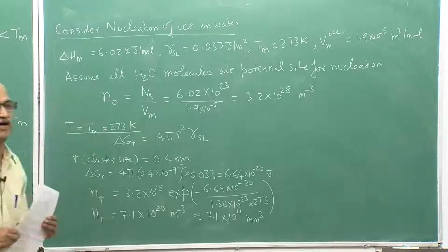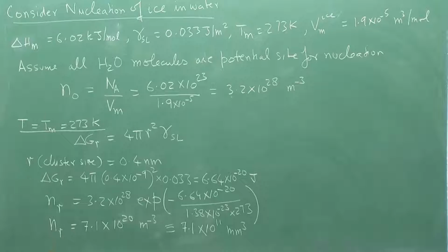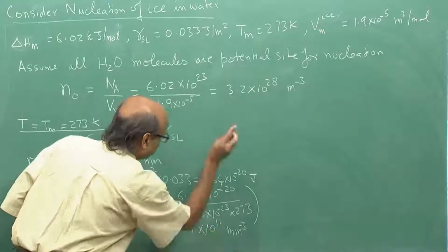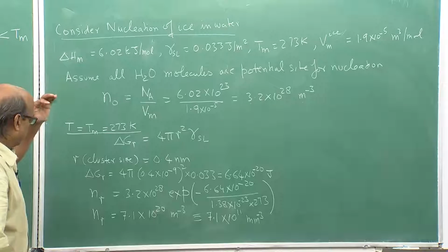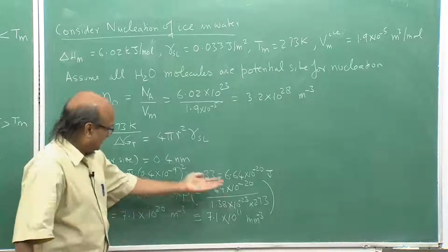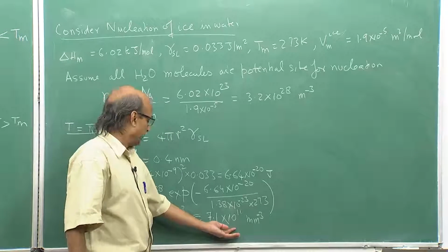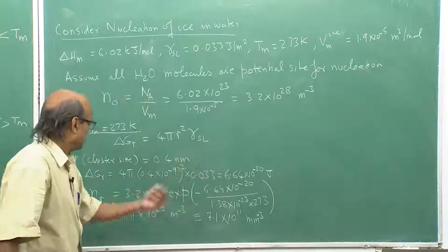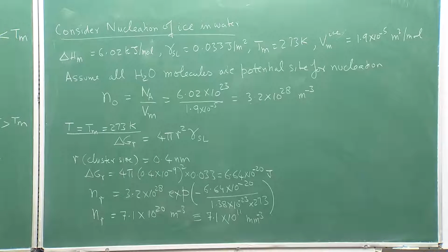So, just in 1 millimeter cube of the system, at a temperature of 273 K, I can expect of the order of 10 to the power 11 nuclei of size 0.4 nanometers.